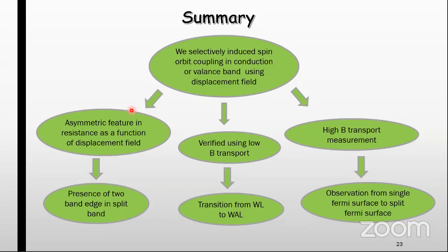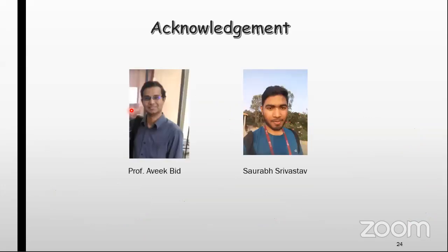Further, we did a low field magnetotransport measurement, and there we saw a transition from weak localization to weak anti-localization depending on the applied external electric field. Later, we did a high field magnetotransport measurement to see the splitting in the Fermi surface in a high spin orbit coupling region. This work I did under the supervision of Professor Aveek Bid and in collaboration with Saurabh Srivastav.